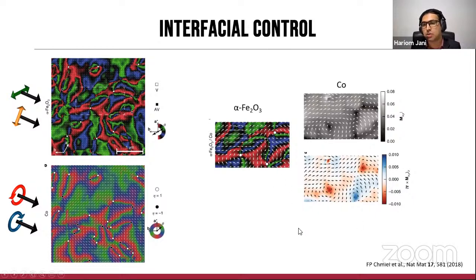And very clearly, the orientation of the swirling can then be analyzed by the curl of these objects, indicating that ferromagnetic objects are also very clearly topological, and they're coupled to the Fe2O3 case here. The key distinguishing factor between this body of work and the previous one was that here the system was prepared as is, and the presence of the cobalt overlayer enforces a significantly strong in-plane anisotropy, and therefore these samples actually do not necessarily exhibit Morin transitions, but they were actually observed right after the work itself.